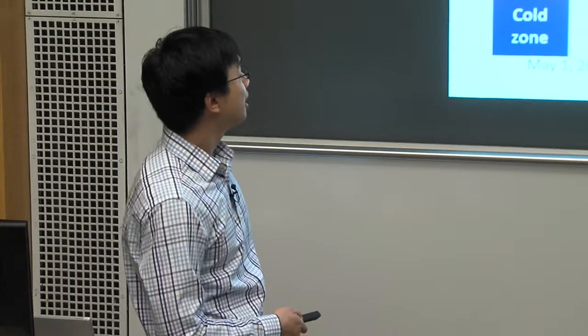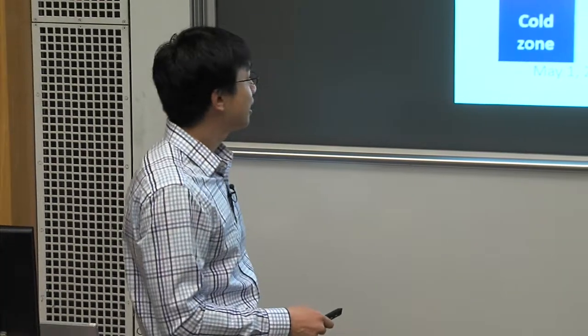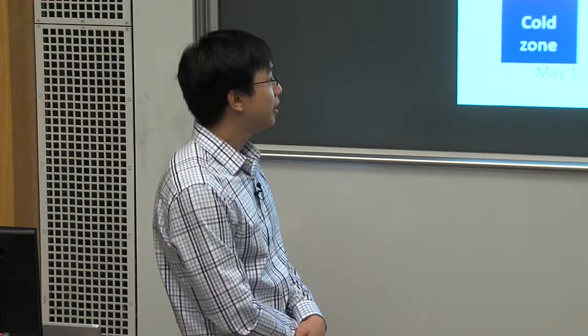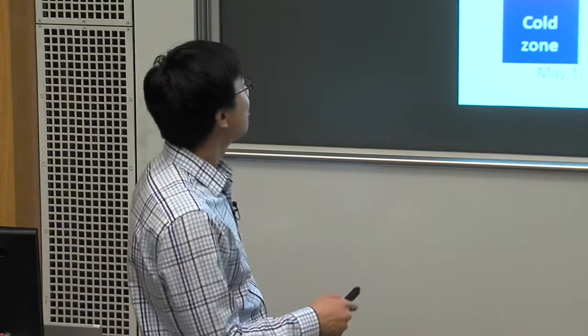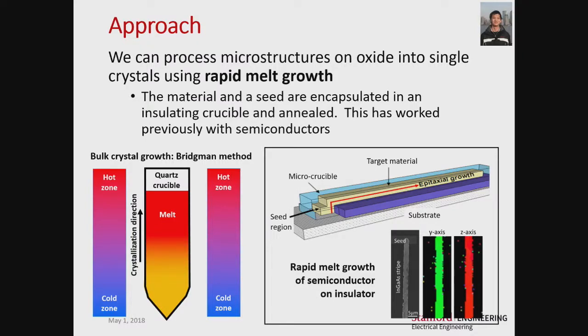Now, if we do want to make high-quality plasmonic structures on chip, we really have to rethink how we do this, especially if we want to make crystalline structures on an amorphous insulator like silicon dioxide. We've been turning to concepts ultimately inspired by bulk metal crystallization. With the Bridgman method, which is how a lot of bulk materials are made, you start with material encapsulated in a quartz crucible, melt it into a liquid, and then slowly crystallize it by putting it in a temperature gradient. Through this process, you get crystal nucleation and then crystal growth in a certain direction.